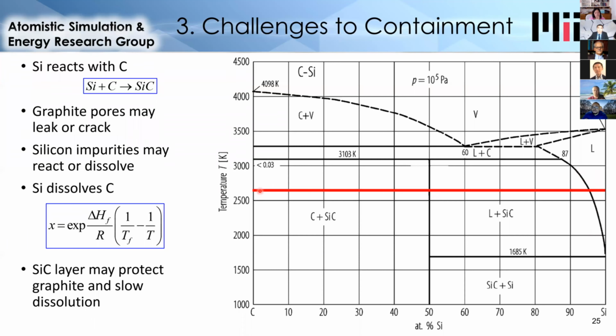So we're operating at a peak temperature of 2400 Celsius, which is about 2700 Kelvin, which is right here. What you see is where this temperature intersects this solubility curve shows that carbon is 5% soluble in silicon at this peak temperature. And while that's a problem, the bigger problem is that this solubility is different than the solubility at the lower temperature in our system, which is around 1%.